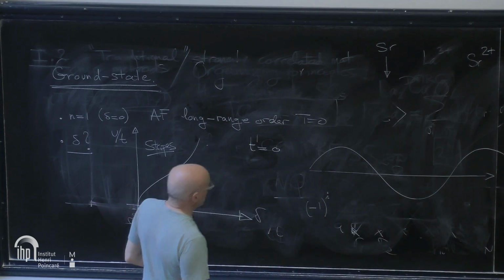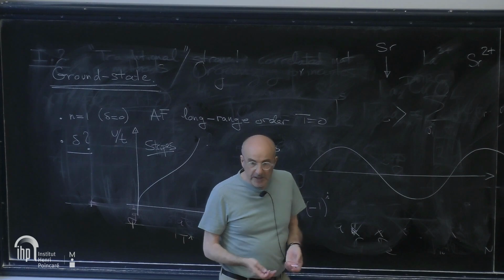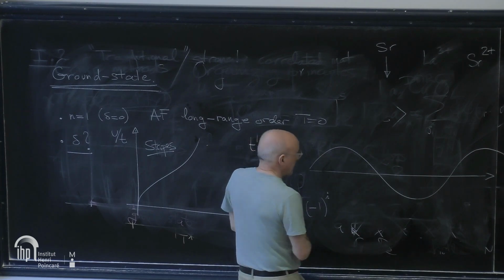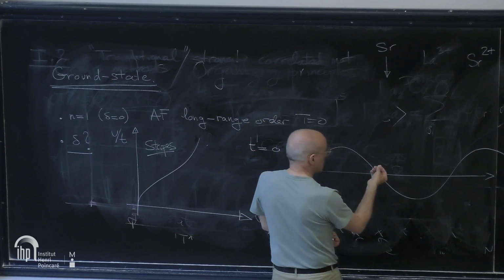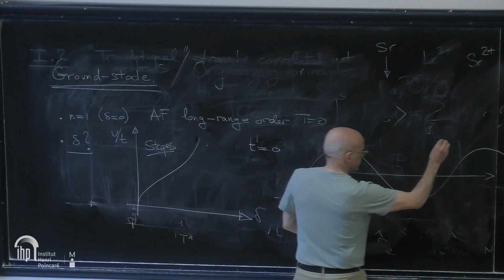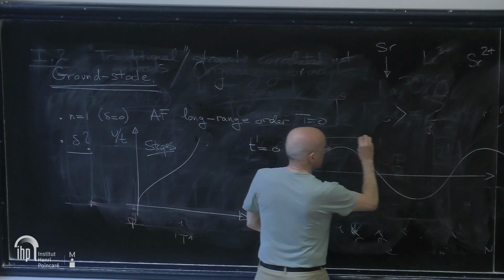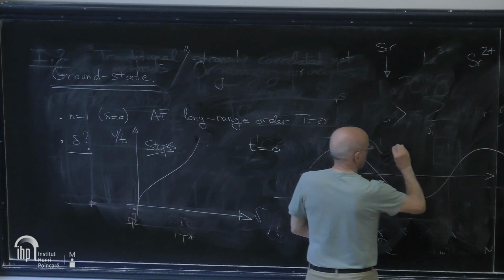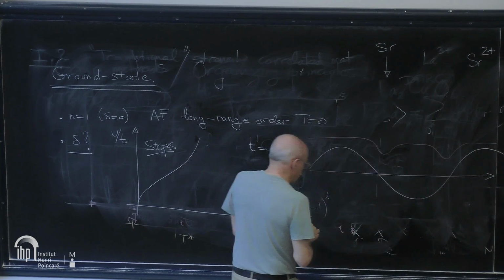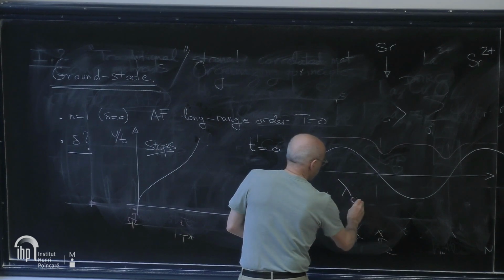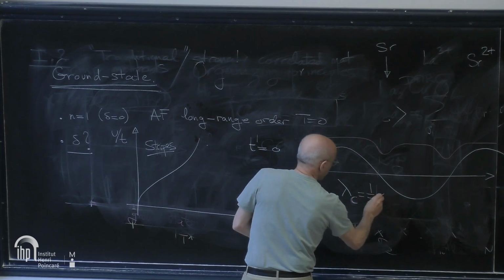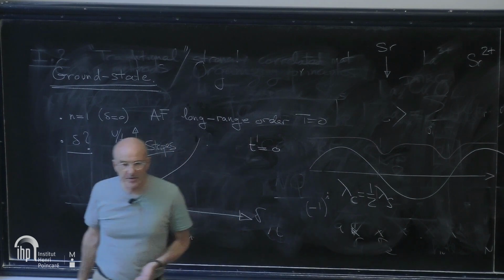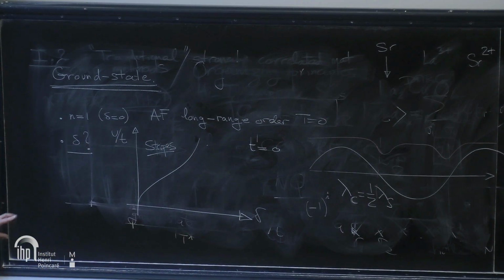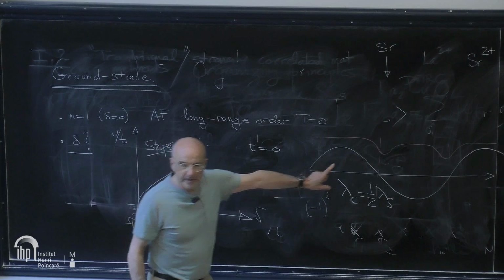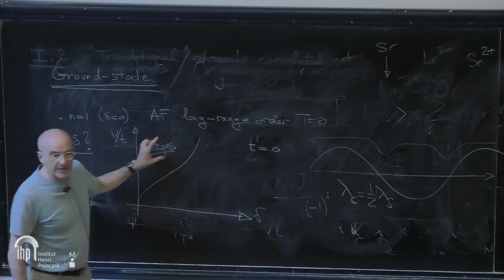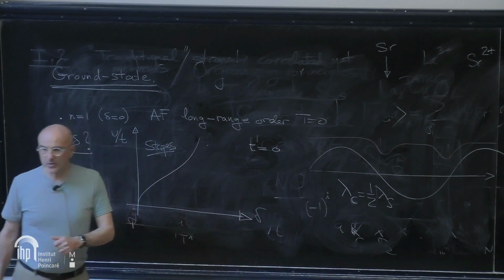And I'm going to draw on this picture the charge density wave that happens. What really happens is that the holes like to be at the nodes of this charge density wave. So the electron density is going to do something like this. And you see that the wavelength of the modulation of the charge is half the modulation of the spin. That is the standard spin pattern, stripe pattern. I'm not telling you that this is always the case, but this is sort of a cartoon.